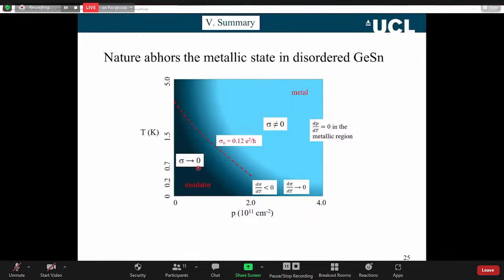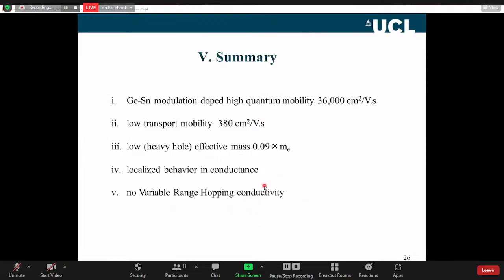In the insulating phase, the conductivity goes to zero. The conductivity becomes so small, it's very, very difficult to measure. But we also see features like the conductance, slightly on the metallic side, loses its temperature dependence. Okay, it's on the metallic side. We also have this turn up in the conductance. There's obviously something else going on there that we don't understand. So in summary,